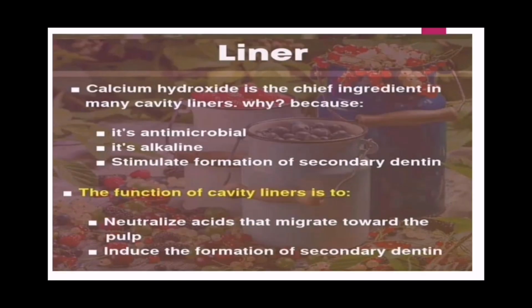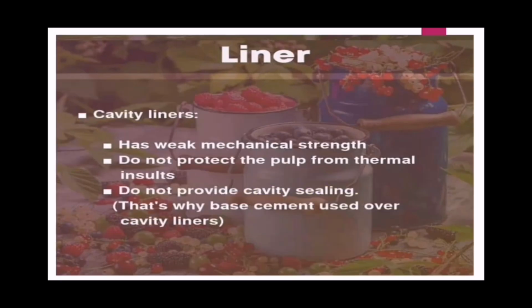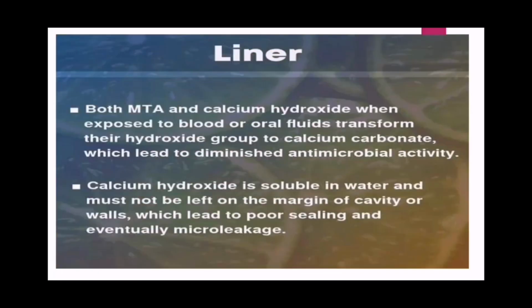Liner. Calcium hydroxide is the chief ingredient in many cavity liners. Why? Because it is antimicrobial, it is an alkaline medium, and it stimulates formation of secondary dentin. The function of the cavity liner is to neutralize acids that migrate towards the pulp and induce the formation of secondary dentin. Liner. Cavity liner has weak mechanical strength, does not protect the pulp from thermal insults, and does not provide cavity sealing. That's why base cements are used over cavity liner. Liner. Both MTA and calcium hydroxide, when exposed to blood or oral fluid, transform their hydroxyl group to calcium carbonate, which leads to diminished antimicrobial activity.